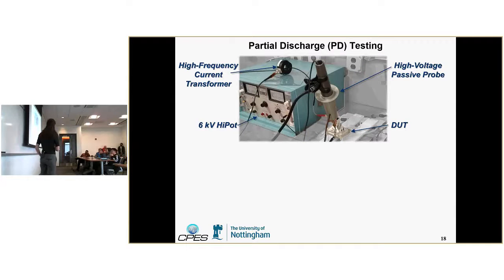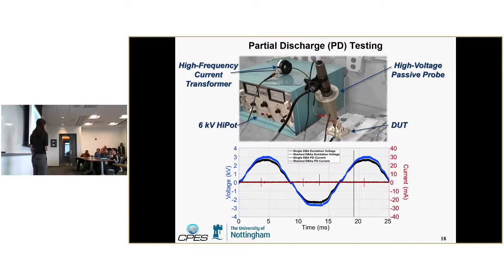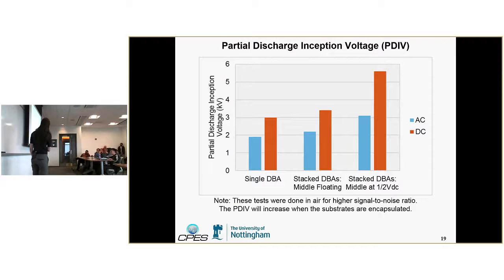And we also did partial discharge tests to verify this. So this is the setup. We've got a high pot tester, a high voltage probe, and we use a high frequency current transformer to measure the partial discharge signals. And this is an example waveform. This is with a line frequency AC excitation, and these are the partial discharge events, these little current spikes.